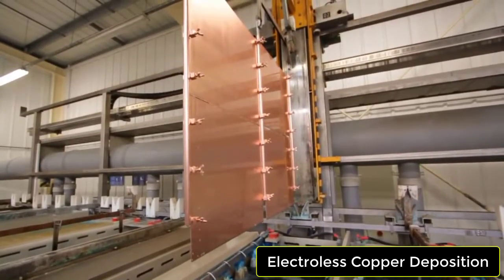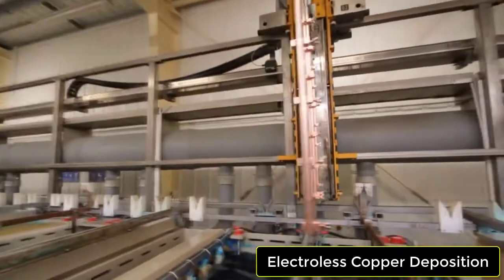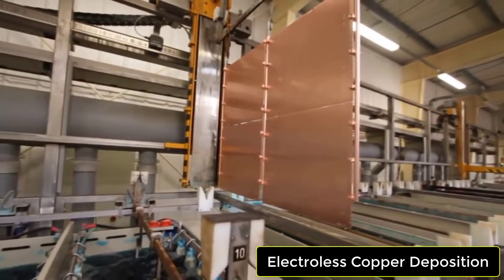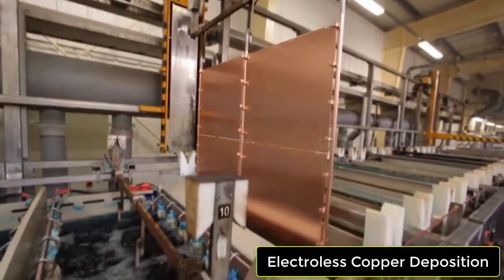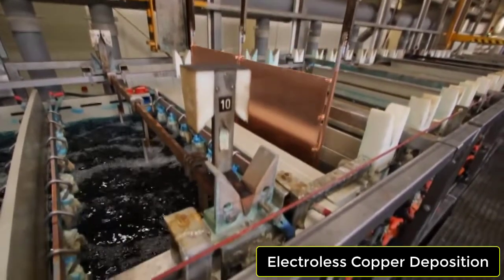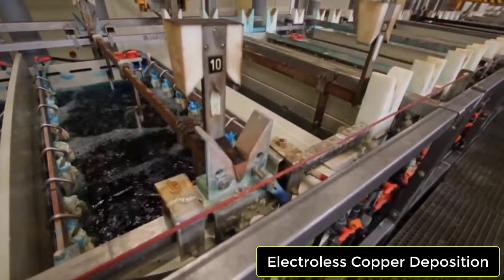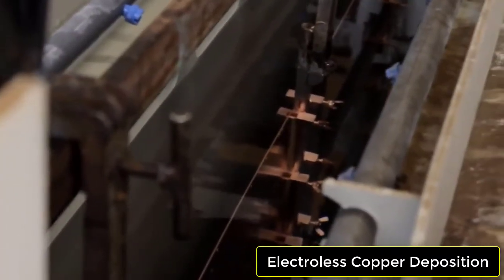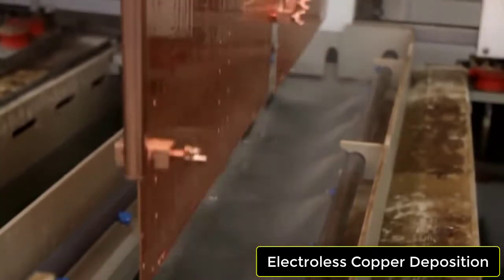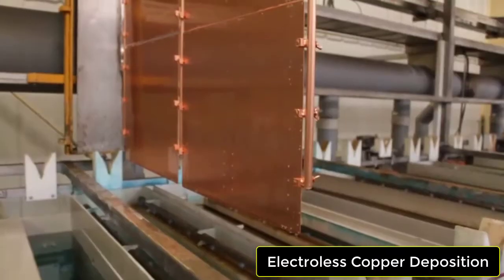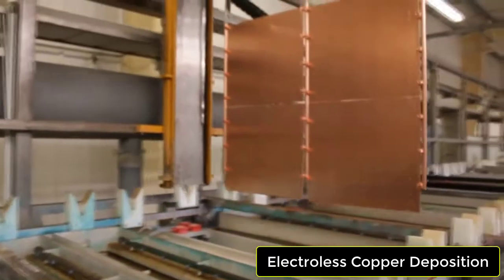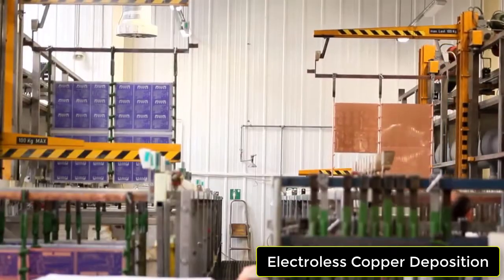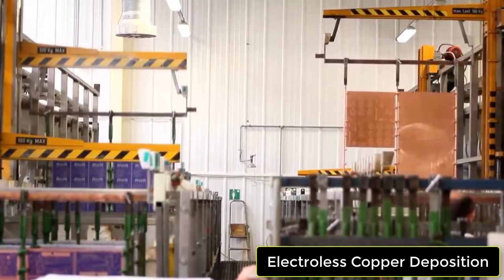This thickness must be electroplated, but the walls of the holes are non-conductive glass cloth and resin. So the first step is to deposit a conductive layer over the hole walls. We use electroless copper. That is, we deposit chemically a layer of copper about 1 micron thick over the walls of the hole, and incidentally across the whole panel. This is a multi-stage process, as you see from the video, with washing steps between the stages. We pre-treat the panel, then we seed the whole wall with microparticles of palladium, and finally deposit the copper.